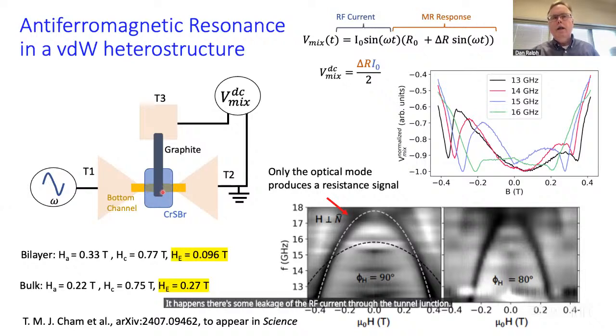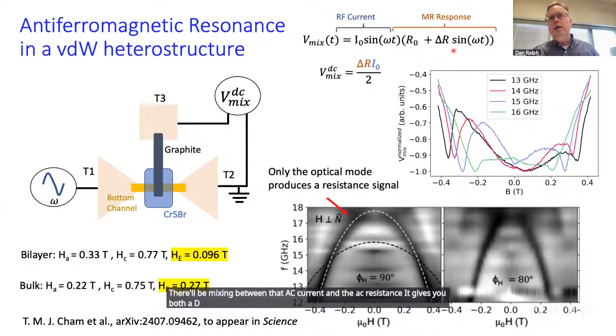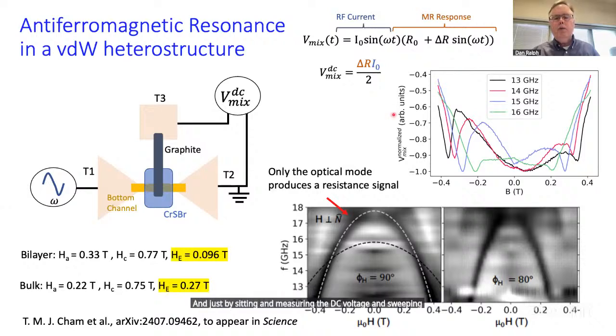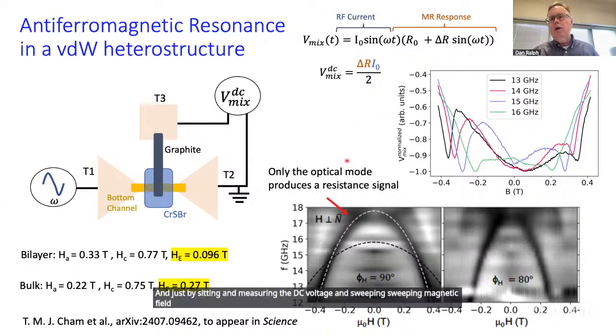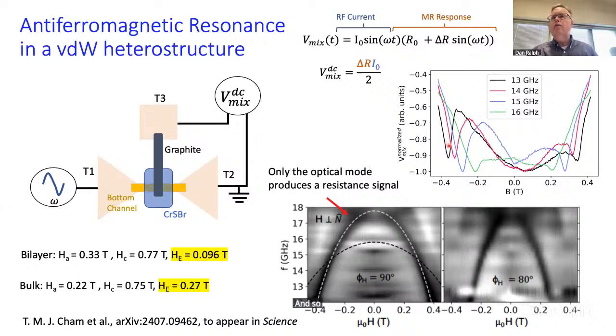So if there are any dynamics of the antiferromagnet at the same frequency as the driving frequency, there'll be mixing between that AC current and the AC resistance that gives you both a DC voltage and a voltage at twice the drive frequency. And just by measuring the DC voltage and sweeping magnetic field at fixed frequency, you can map out what the modes look like. And so on the right here, I just show what this DC mixing voltage is as a function of magnetic field at several different frequencies of the excitation.